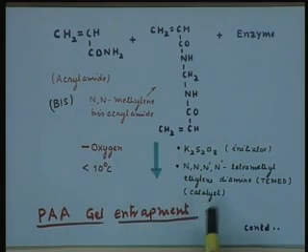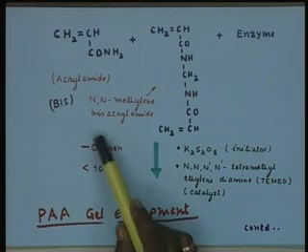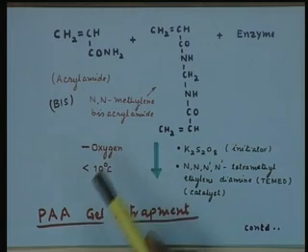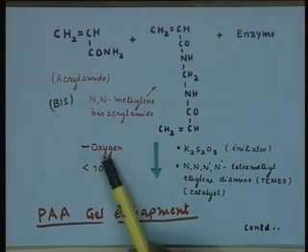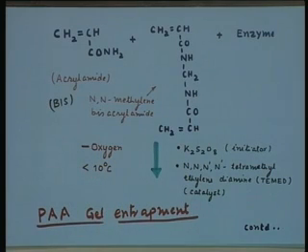And for this mixture, the 2 parameters which are very important to control here are, first, the absence of oxygen. The presence of oxygen inhibits the polymerization reaction. So, it is very important that all the reagents that are being used are free of oxygen. Basically, if you just bubble nitrogen through the reagents, you can get them free of oxygen, but even traces of oxygen can reduce the degree of polymerization in the polymerization reaction. And the second parameter is that the reaction must be carried out at less than 10 degrees centigrade. Of course, the reaction temperature will control the reaction rate, so it carries out the reaction at a slow rate, and it has also been seen in the polymerization reaction that the slower the rate, the degree of polymerization can be taken up to a higher level.